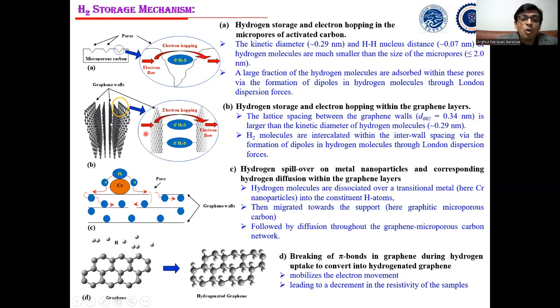That means the more graphene layers or micropores you have, the more dipole formation occurs. Therefore, more and more hydrogen molecules are attached through this dipole formation. Therefore, the resistivity decreases and the electron hopping increases. So this is the reason that with increasing hydrogen storage, the resistivity of the system decreases.